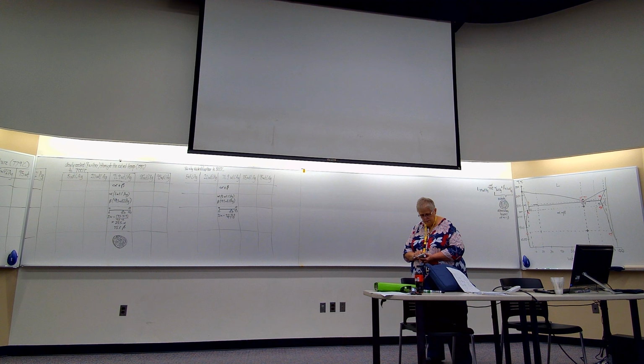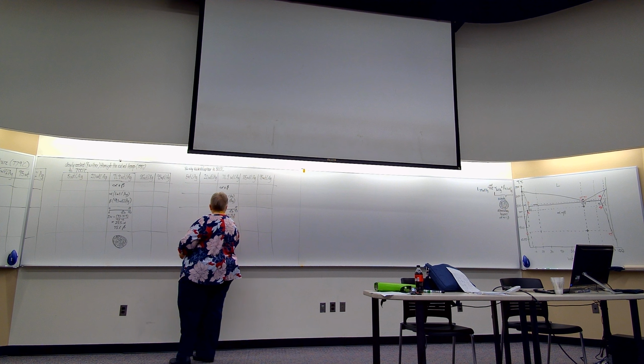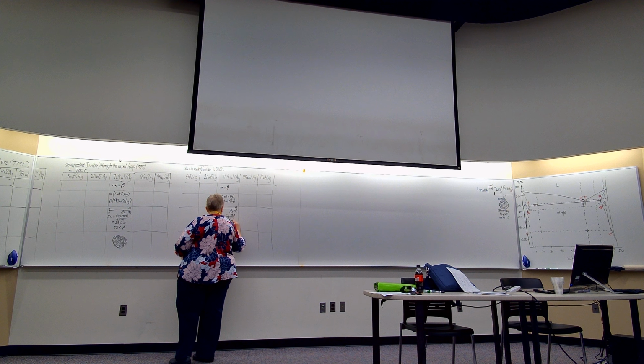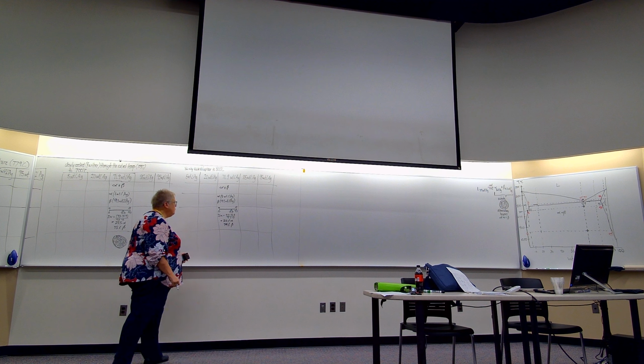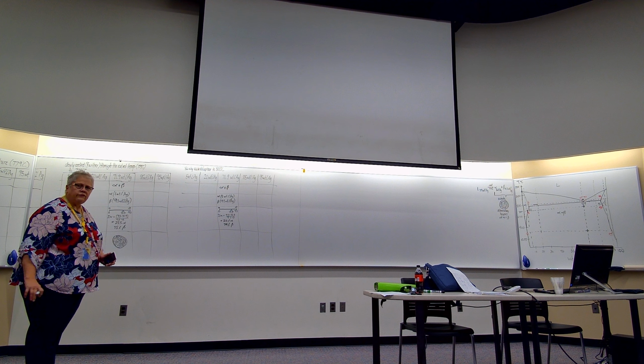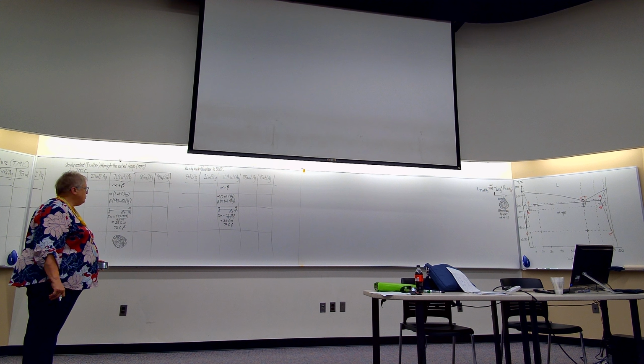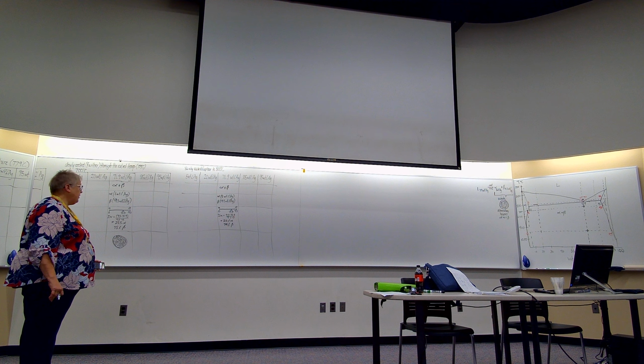So we're at 26% alpha and 74% beta. So slightly different amounts of alpha and beta. The layers of alpha have just gotten thicker, and the layers of beta have gotten thinner. But not that much different, and it would look just like the earlier one.